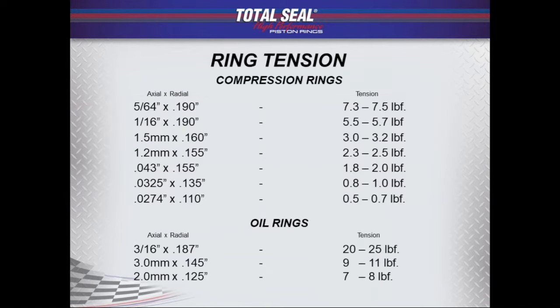I wanted to show you this graph, and it talks about ring tensions, again trying to show a little bit of history of where rings have gone. A 5/64 ring, and these were all done at 4.185 bore, by the way. The 5/64 ring with 190 depth, ductile moly ring, checking at about 7.3 pounds of tension, 7.5 pounds.